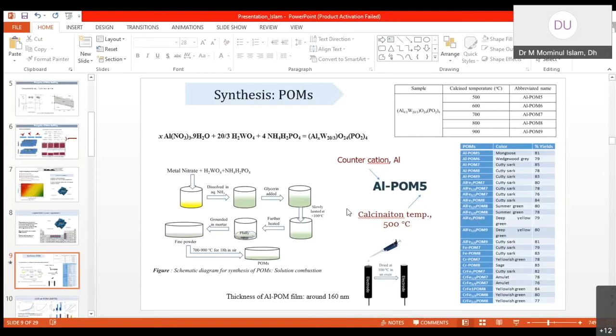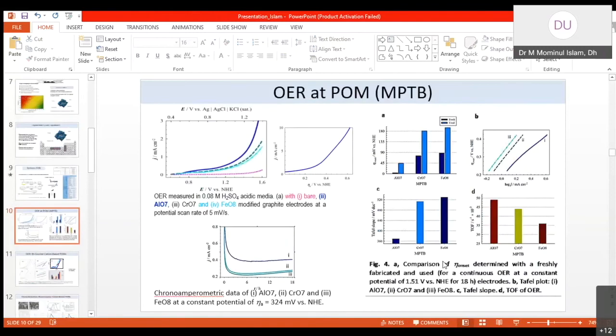This catalyst is synthesized and then cast on the electrode surface with a film thickness like this, and used for the water oxidation reaction or the water splitting reaction. Here is an example of the oxygen evolution reaction, with the linear sweep voltammogram and chronoamperometric tests to get the stability. After analyzing all of this, we summarize the results here: the onset potential, Tafel slope and Tafel plot, as well as the turnover frequency for the oxygen evolution reaction.